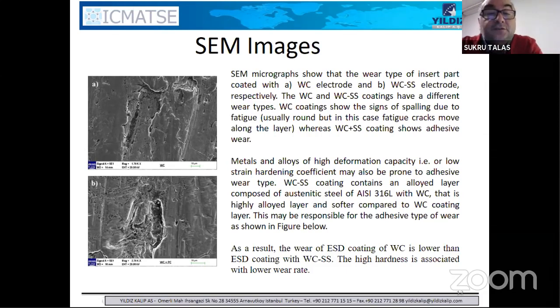So hardness increases, and scratches are almost gone. Because the surface hardness is high, the wear type also changes. The difference between these two is the alloying, or two different layers. One is softer at the bottom, and the other one is hard. So that's another advantage and disadvantage.